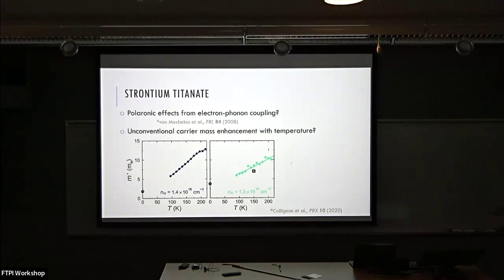So there's been some measurements of, so this is from Seebeck effect. You can extract the effective mass under some assumptions. And then what you get is that it goes up very quickly with temperature. So this is a huge mass enhancement. You go from 0 to only 200 Kelvin. So we go from something like 2 to above 10 M star. And there's been some thinking along the lines, and this has to do with polaronic effects. The Electron-Phonon coupling, which is pretty strong, that somehow these electrons get dressed more as the temperature increases.